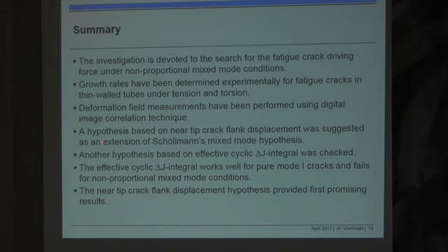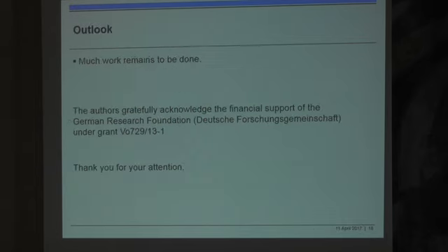We came along with a hypothesis based on what I call near tip crack flank displacement, which is suggested as an extension of Schöllmann's mixed mode hypothesis, and the other hypothesis based on the J effective was also checked. However, this effective cyclic J integral works well for pure mode 1 and fails for non-proportional mixed mode conditions. And the new one is promising, as I mentioned.